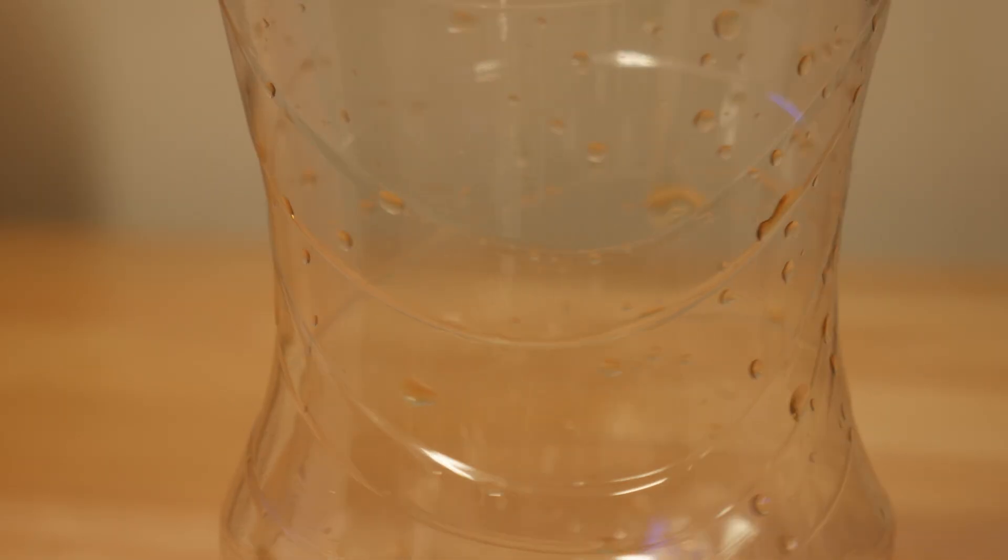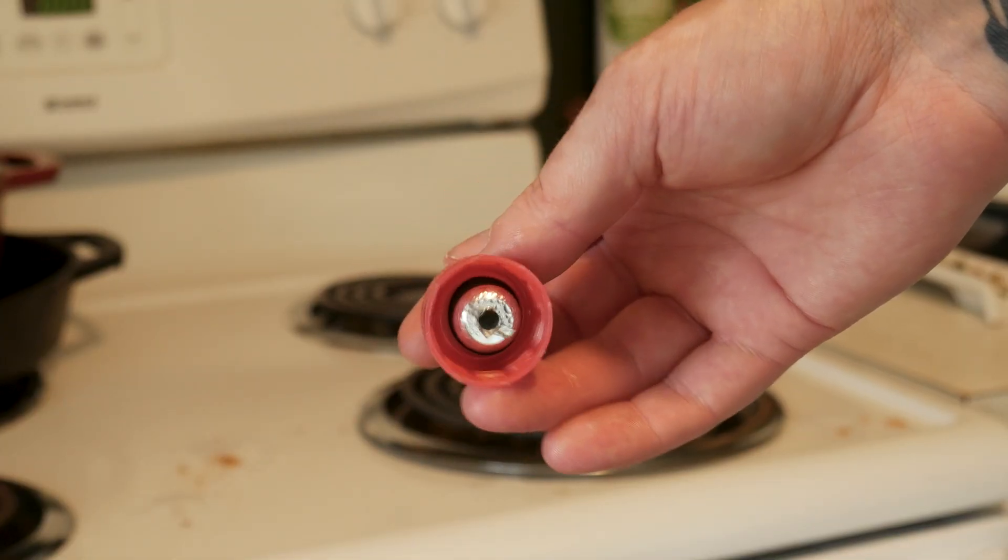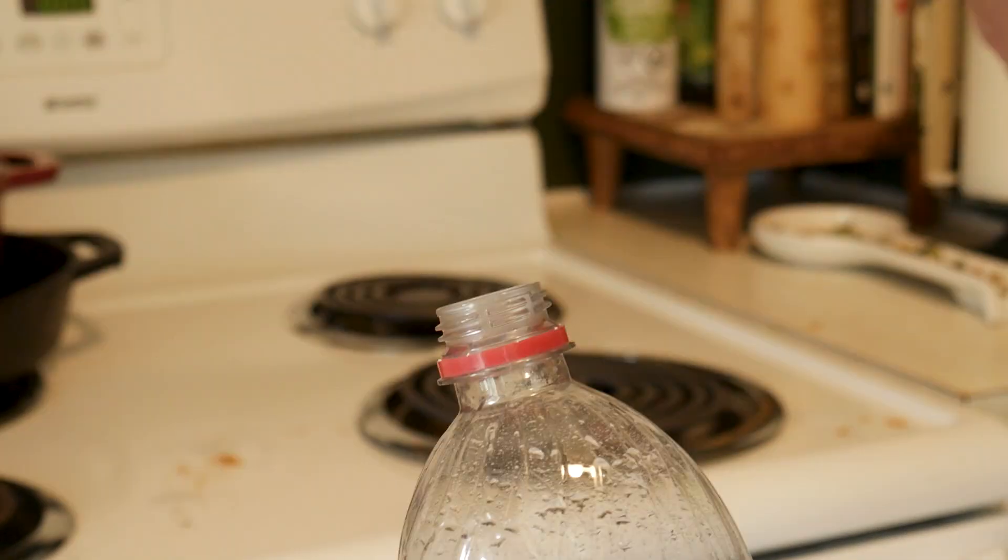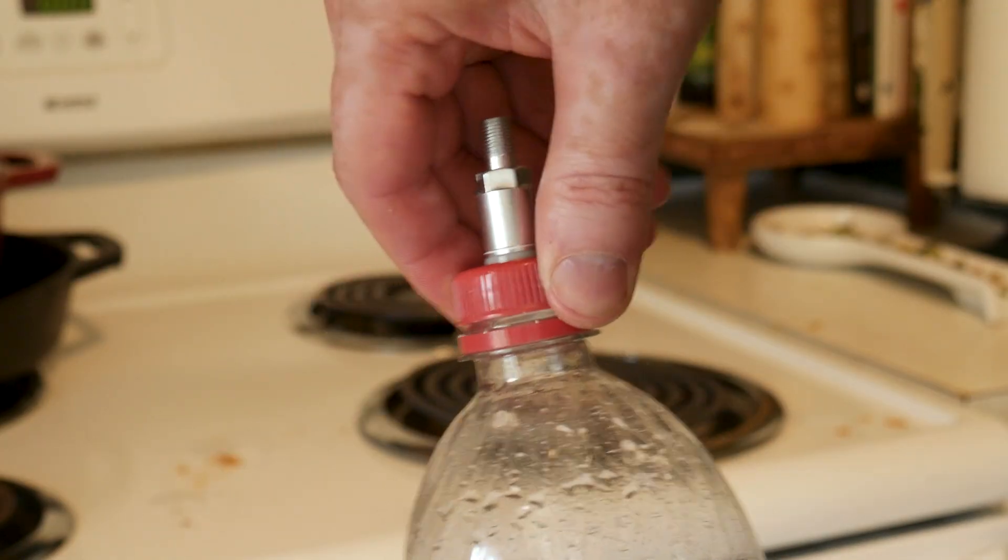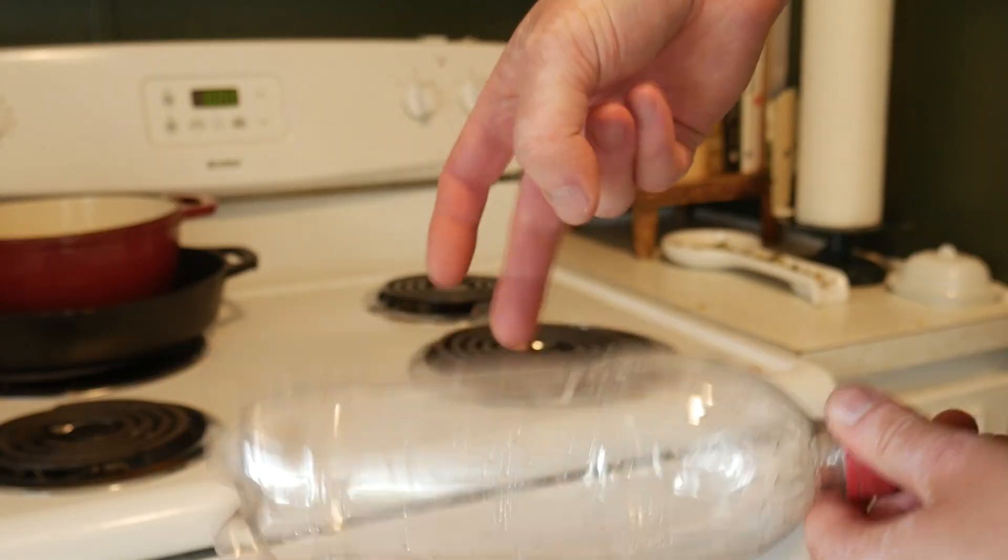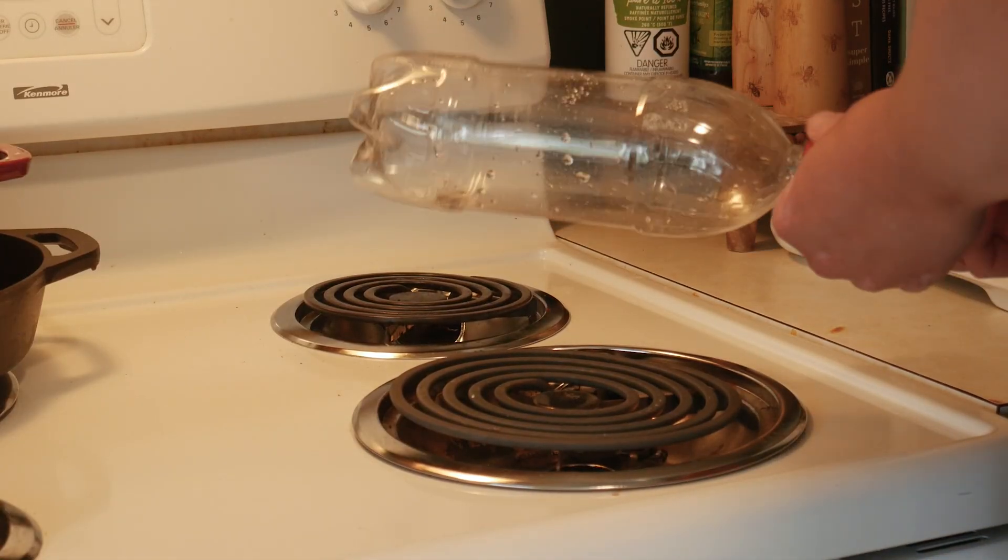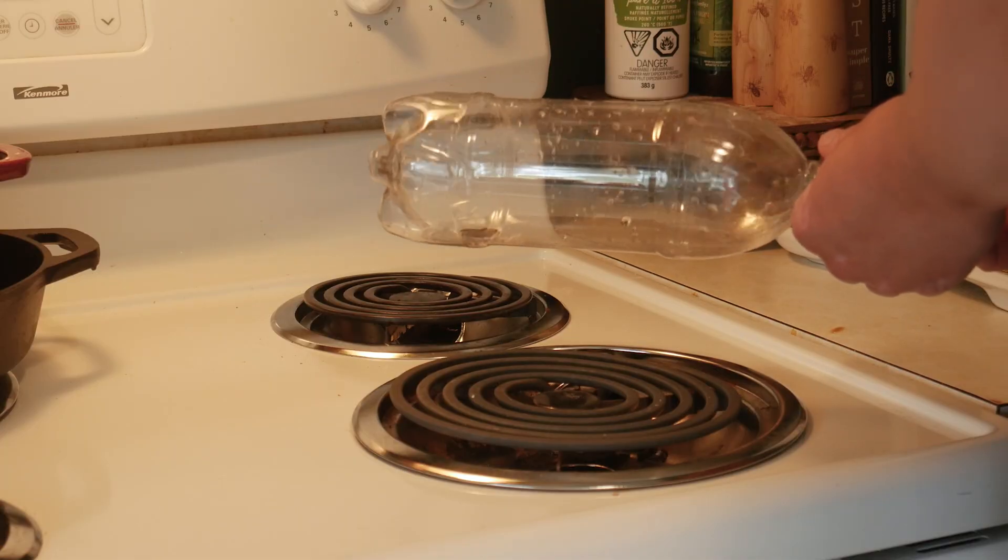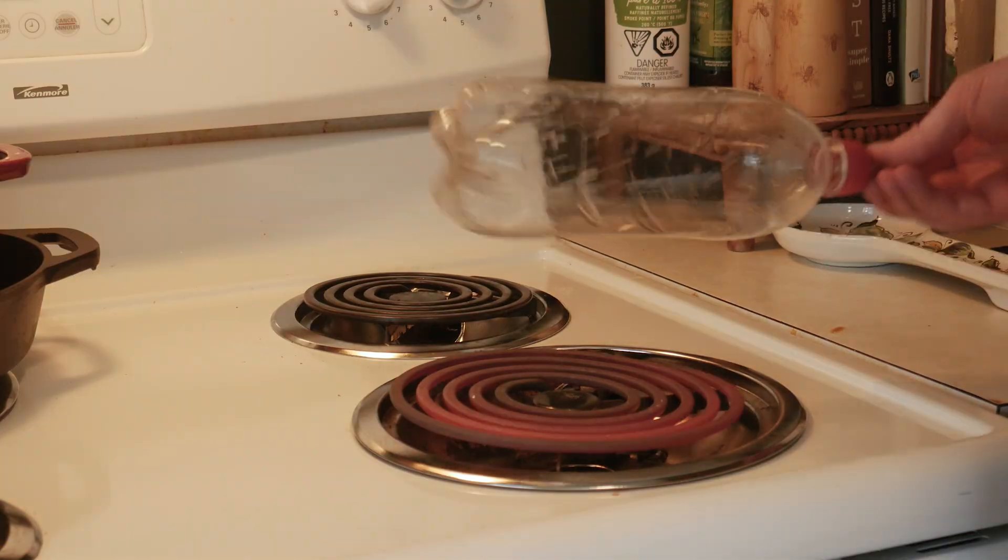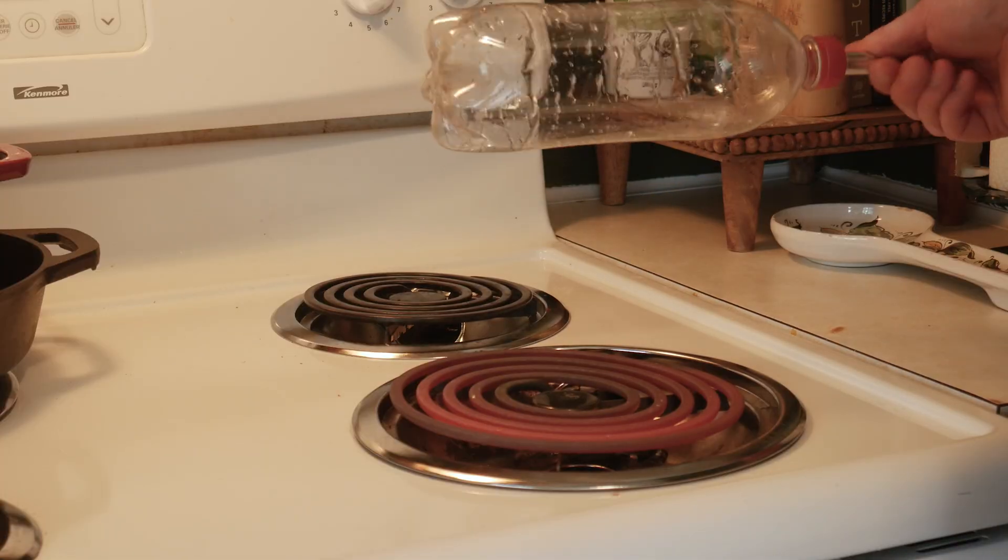Now we need to cut the bottle into even strips, but first we have to get rid of any ridges or embossed logos. There's a few ways to do this, but I found the following method to be the most effective. I added a tire valve to a bottle cap and used a bike pump to add just a little bit of pressure. This helps prevent the bottle from shrinking or collapsing. Then, I held it over my stove burner, turning it constantly. After about a minute, the ridges were smoothed out.